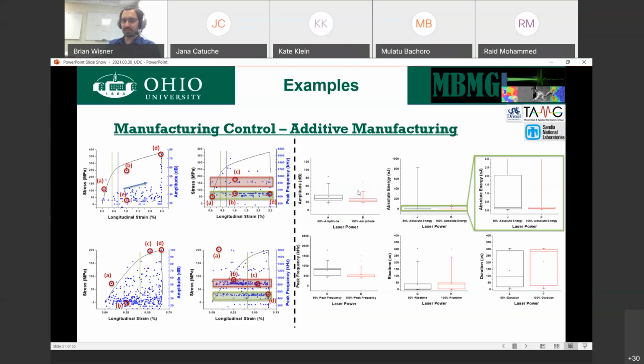If you compare the trends, you look at it in terms of amplitude, you look at it in terms of all of these, there's a lot that's comparable. Amplitude's about the same. Energy is very different between the two materials. Rise time's about the same. Duration's pretty much the same, though you do see a difference in the mean. Peak frequency is different. Why do we have these different mechanisms? What's causing that? And how do we tie that back to laser power?